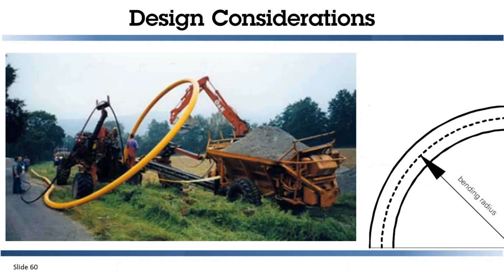Another nice thing about plastics is that they are pretty flexible, and so we can build that into our design. If you have an outdoor installation, you can reduce or eliminate elbows used in the field by simply bending the pipe. Typically, it's about 20 to 30 times the piping diameter, depending on the material and temperature, where you can actually bend the pipe around a corner. Useful for large outdoor installations.